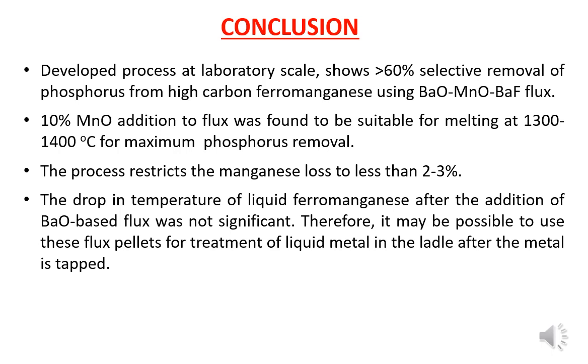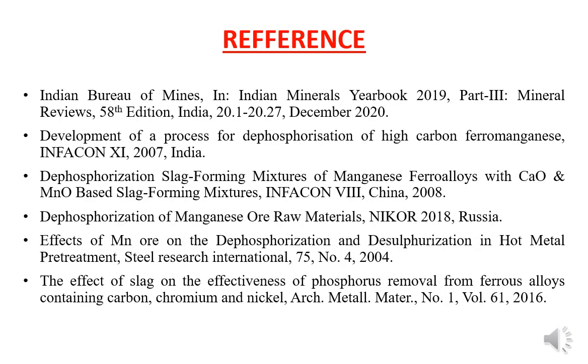The drop in temperature in liquid ferromanganese after the addition of barium oxide based flux was not significant. Therefore, it may be possible to use these flux pellets for the treatment of liquid metal in the ladle after the metal is tapped. Reference.